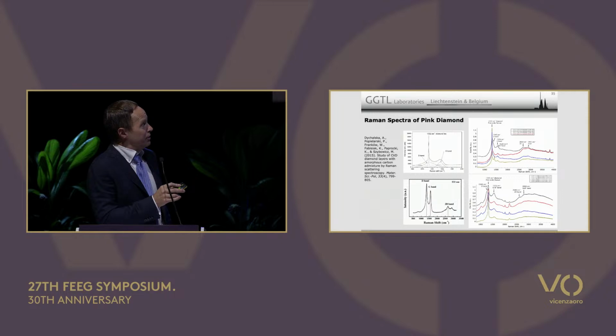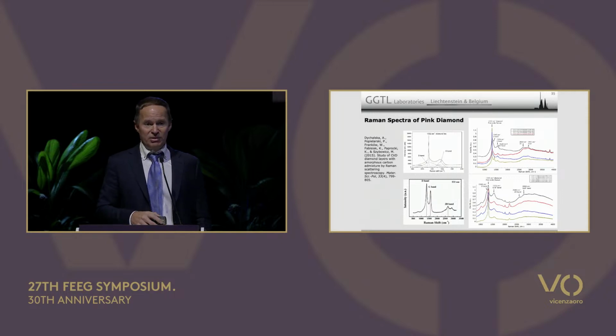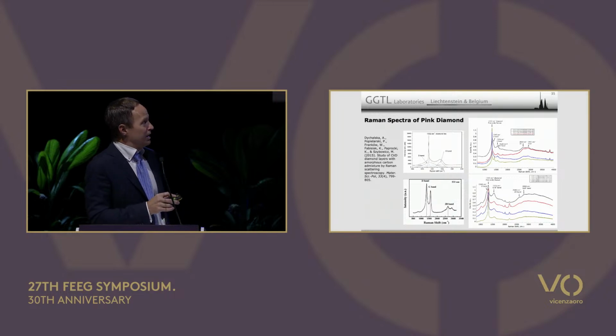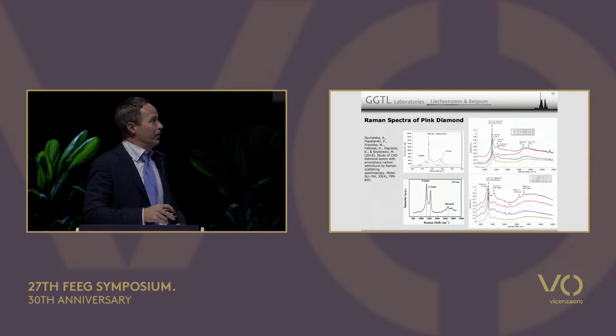So here you see the first order Raman peak. A Raman peak in a diamond is usually just a very sharp, narrow peak. In pink diamond, on the other hand, it's this weird asymmetric thing here. And that's the case for all type 1 pinks. Here at 635, you see it even more dramatically.